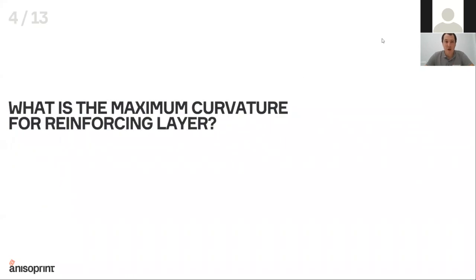What's the maximum curvature for the reinforced layer? The fiber can be bent, and it is actually bent every time it's printed. It's bent in the nozzle at a 90 degrees angle, at a radius of less than 1 millimeter. When we're printing infills, the fiber sometimes has to turn at sharp angles, and then there is a small curvature, of course, so it's not completely an angle, about 1 millimeter radius.